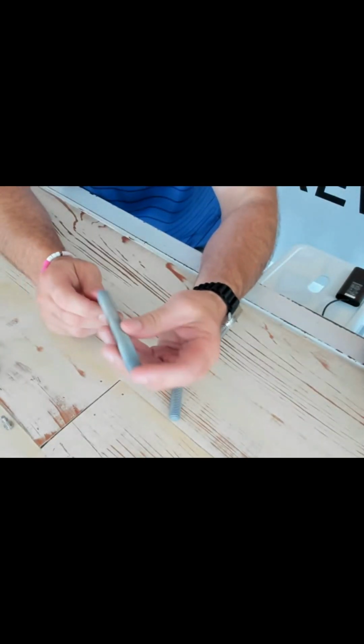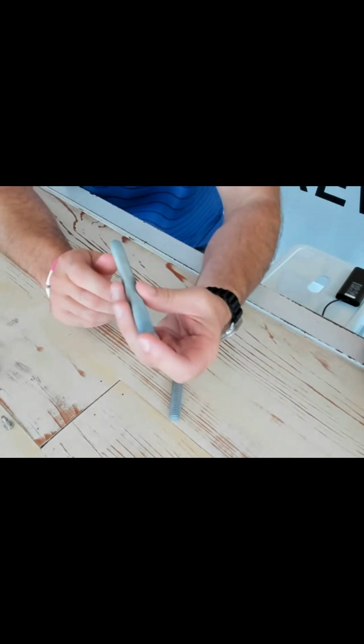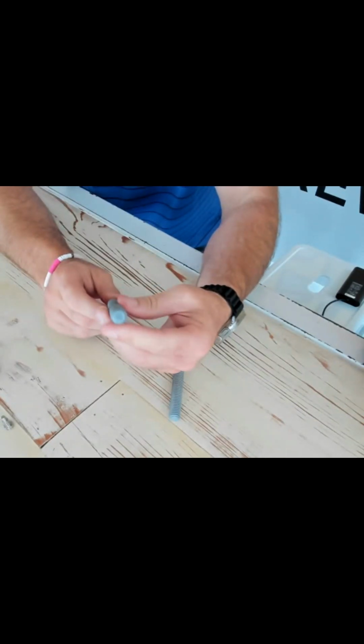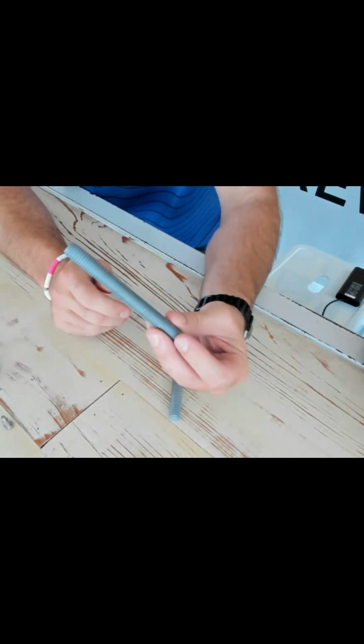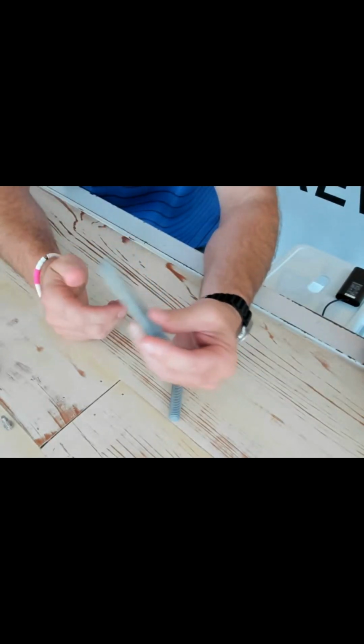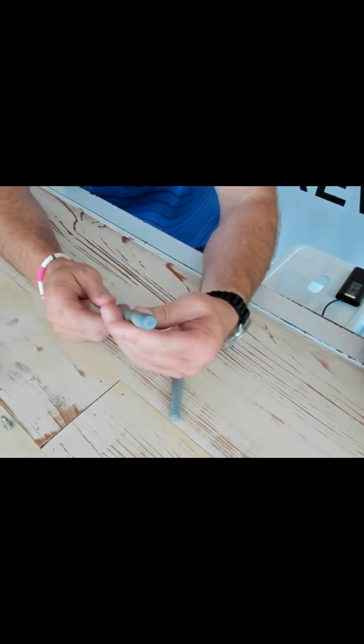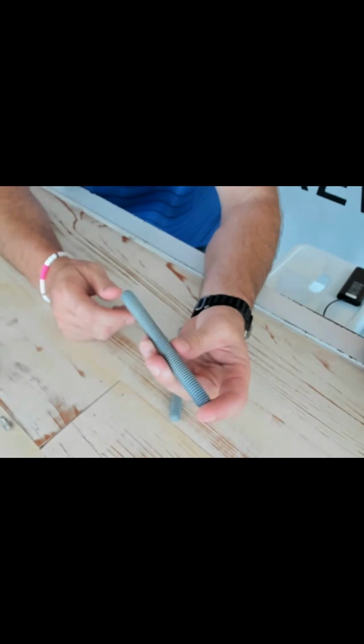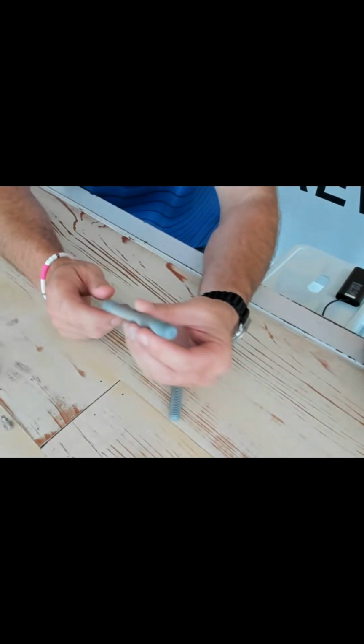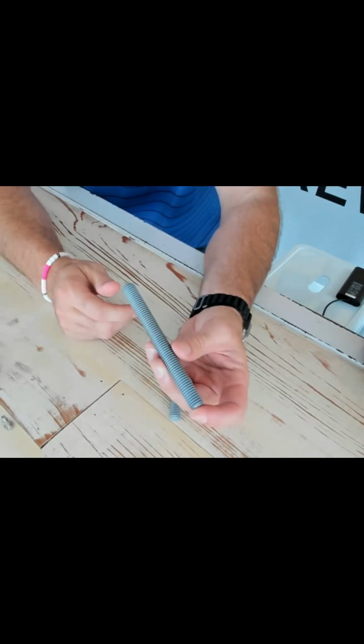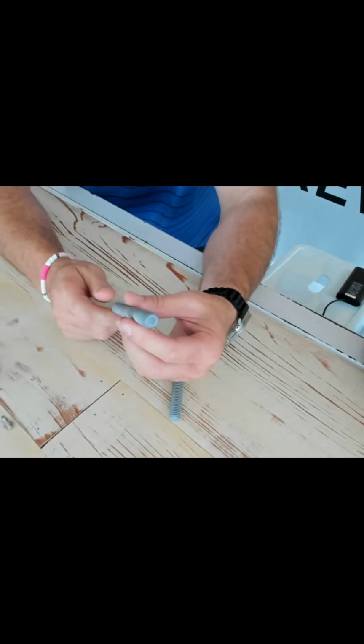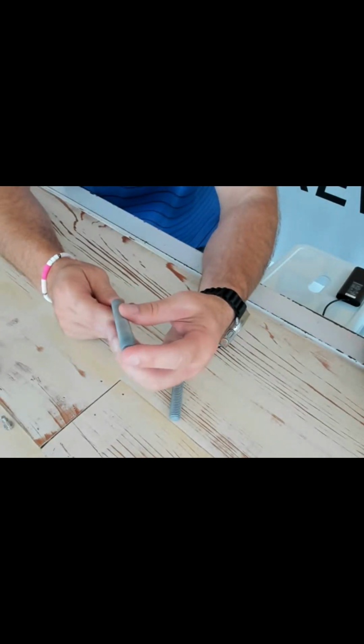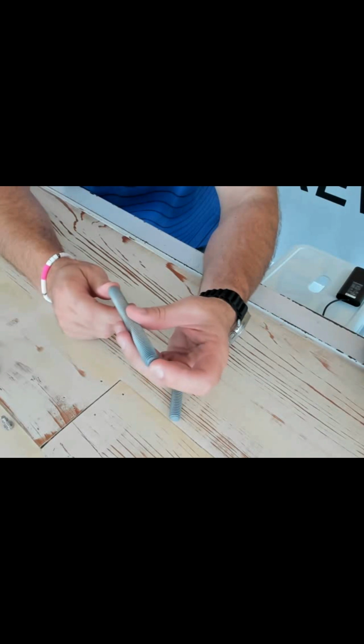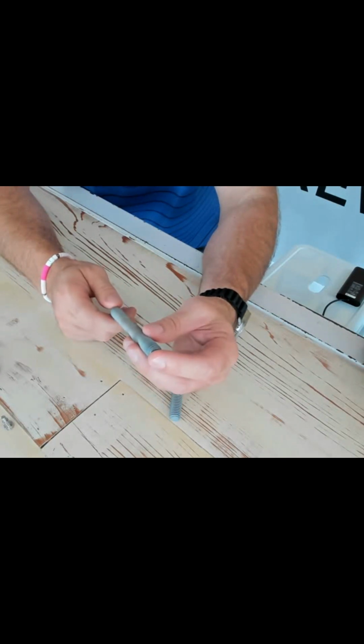And so this is pretty specific to alloy bolting, alloy steel, right? So B7, L7, you do not NanoGalve stainless. It's only going to adhere to an alloy. It's typically this gray, kind of dull matte color. Sometimes it'll have a bluish hint to it when it gets out of the bath. But we do these quite a bit, right? Mm-hmm.